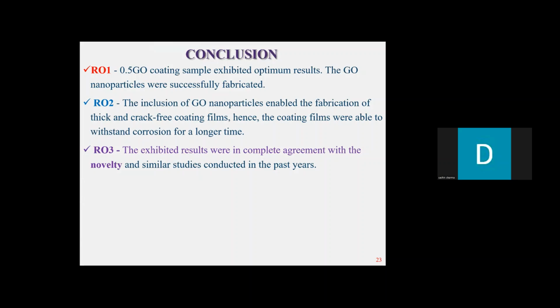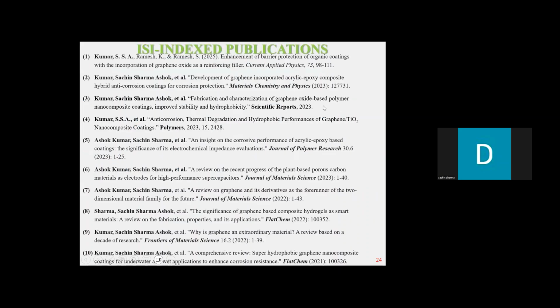So the conclusion here is that among all the coating samples, the 0.5 GO exhibited optimum results. The nanoparticles were successfully fabricated using the new method. The inclusion of graphene oxide nanoparticles enabled the synthesis of thick and crack-free coating films, and they were able to withstand corrosion for a longer period of time. And the results exhibited here were in complete agreement with the novelty and similar studies that were conducted in the past. So these are some of my publications that were published with respect to the corrosion studies.